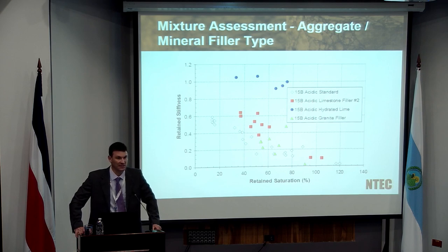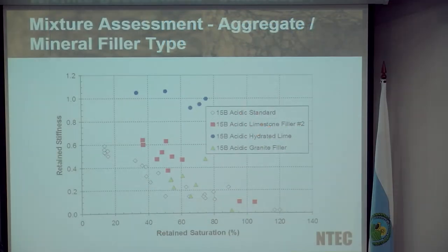into the bulk material testing that we did, a test that allows us to measure retained stiffness, where retained stiffness, very simply, is a stiffness ratio between a dry material stiffness and the stiffness that material then experiences after it's been moisture damaged. So effectively, it's an indication of how much stiffness decrease we've seen for our material. And in this particular test, we can take that retained stiffness, and again, lots of tests do that. AASHTO T283 measures the retained strength, but again, you could do a retained stiffness test. But the SATS test allows us to look at different saturation levels.